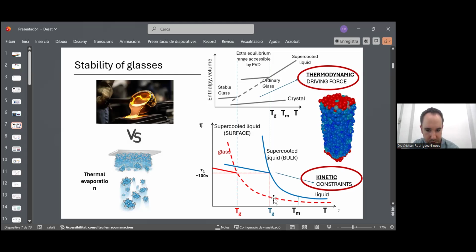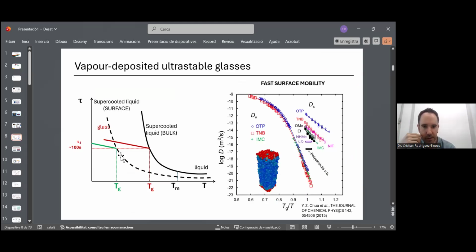You see that the relaxation time of this surface layer, because it is not surrounded by many other molecules and lies on the surface, is much shorter. It can equilibrate faster, it can stay in equilibrium faster. So we can go to lower temperatures by keeping this surface layer in equilibrium, and therefore we can prepare a glass which has lower enthalpy, so a more stable glass. So this is the basic idea behind the ultrastable glass, taking advantage of this faster surface mobility.